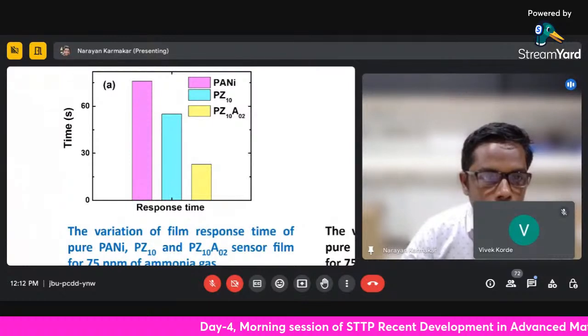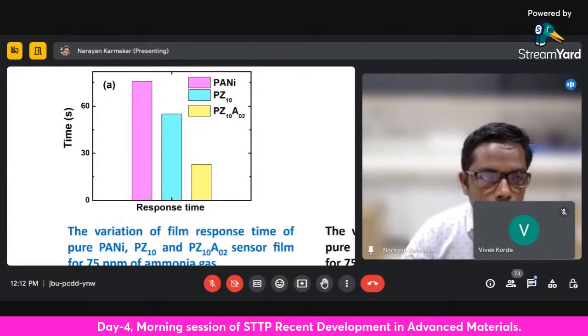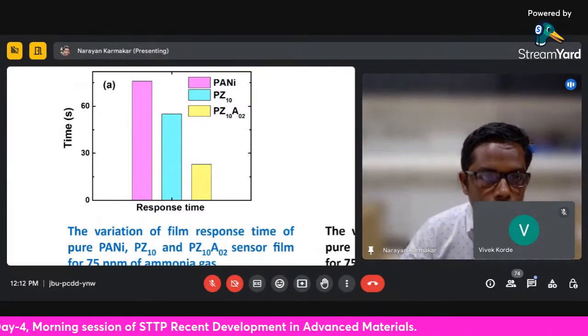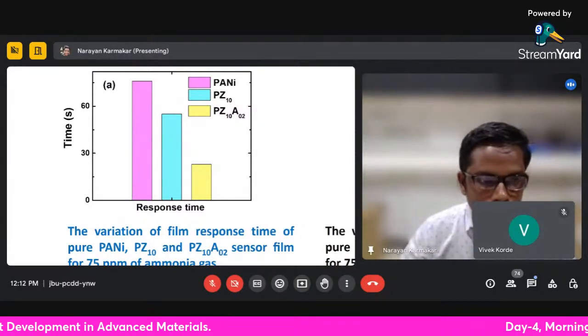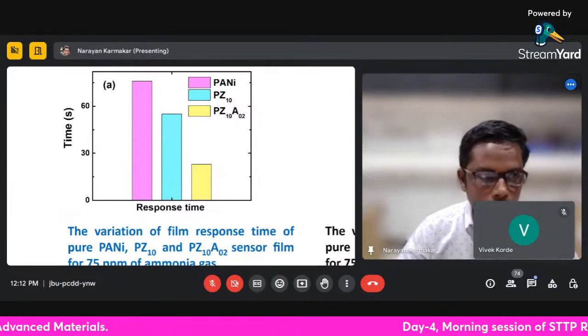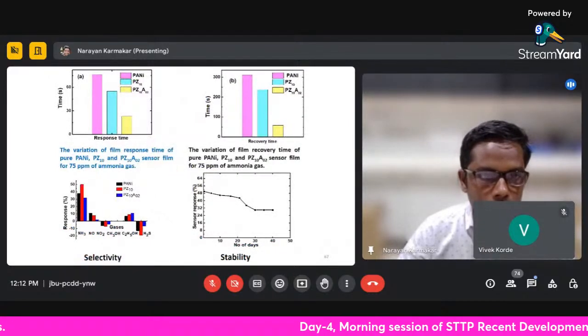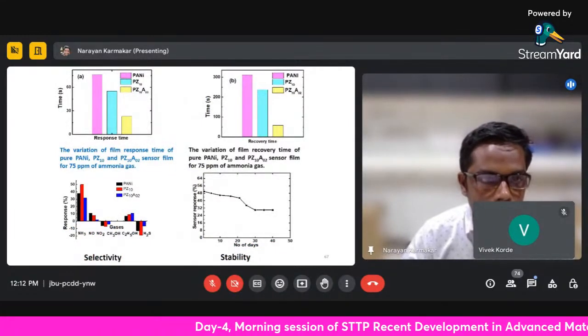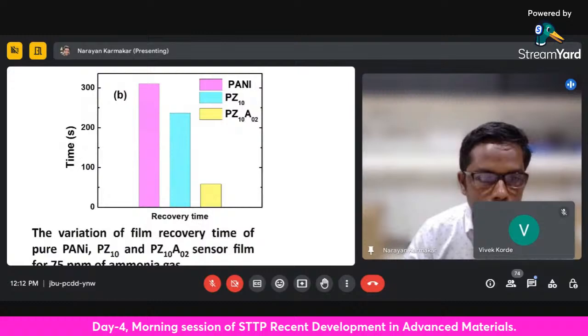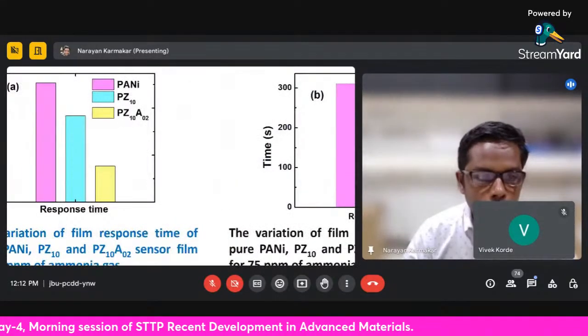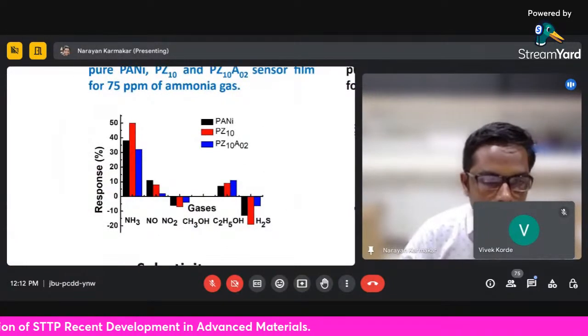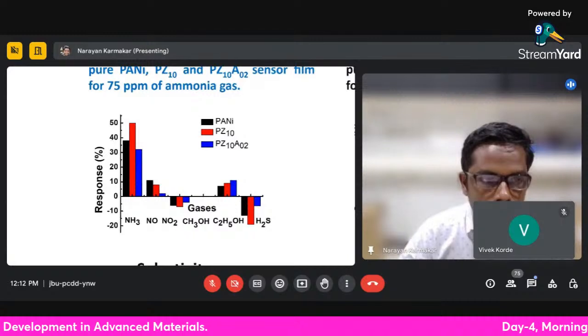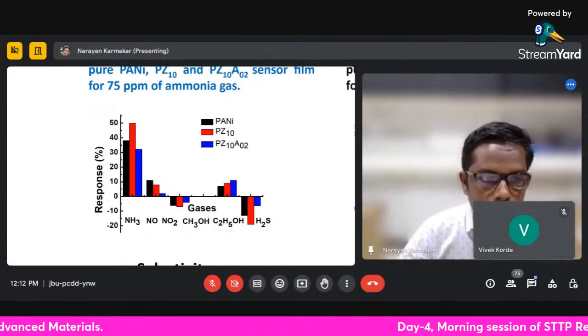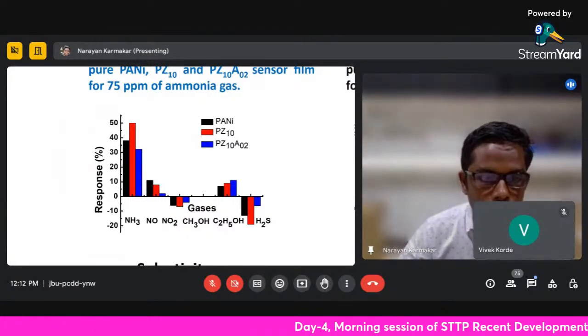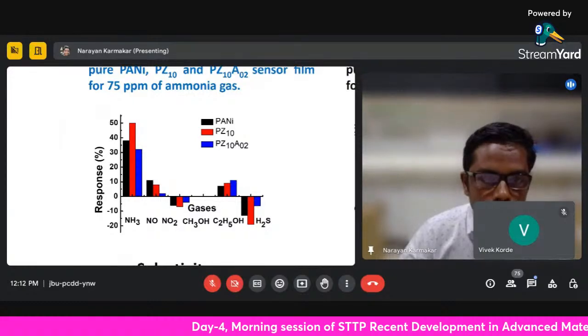We can look at this: the response time is drastically reduced when you compare it with the PANI and the PZ10. Also, you can see the recovery time has also decreased a lot. But the selectivity is good, it's more selective to this ammonia gas, though it also shows a small response to H2S gas.